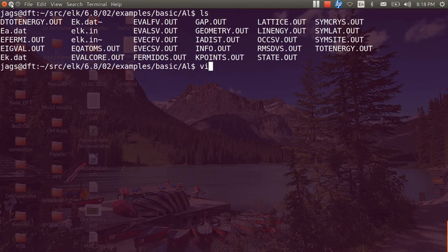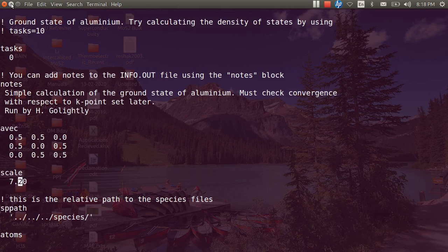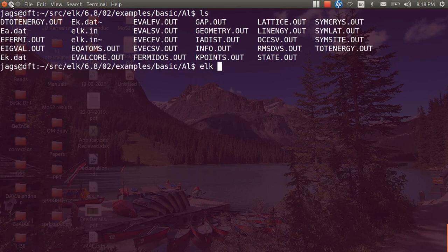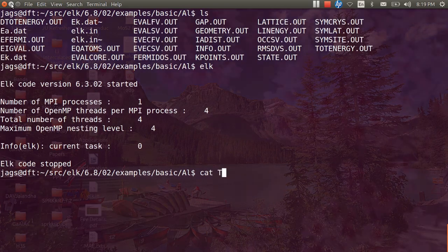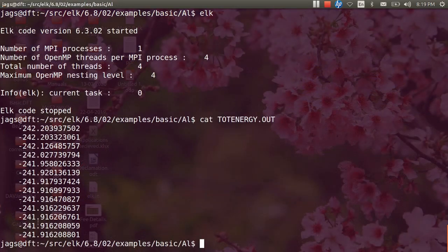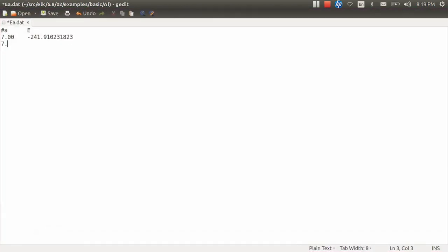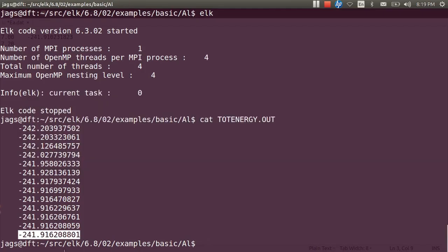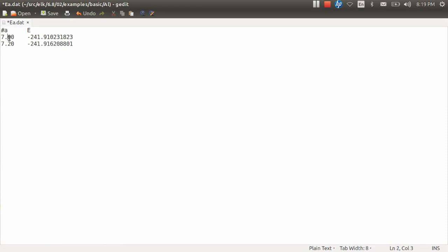Now let me do it quickly in VI editor. Another value, let us put, say, 7.2. Run the calculation. We did nothing but just changed the lattice constant. Every other parameter is exactly the same. Now this is the energy corresponding to lattice constant of 7.2. I will be saving this here. Now you should see that as this was a compressed crystal structure because lattice constant is just 7.00, this is a crystal structure which is relatively less compressed. So there is a decrease in energy. 241.916. So there is a decrease in energy. I hope you understand what is the meaning of decrease in energy - energy is lower in that case.